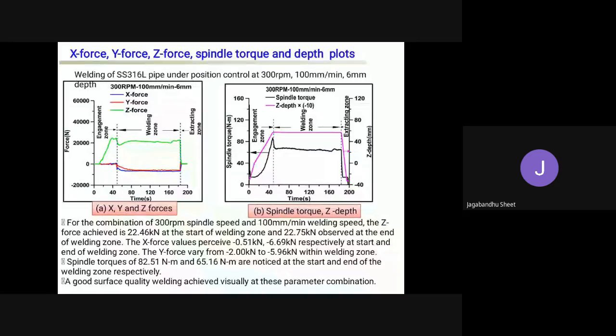And the X force is varying from minus 0.5 kilonewton to minus 6.69 kilonewton, and the Y force is varying from minus 2 to minus 5.96 kilonewton at the start and the end of the welding zone. So in this parameter condition, no defects have been shown. A good quality surface has been achieved in this friction stir welding process.